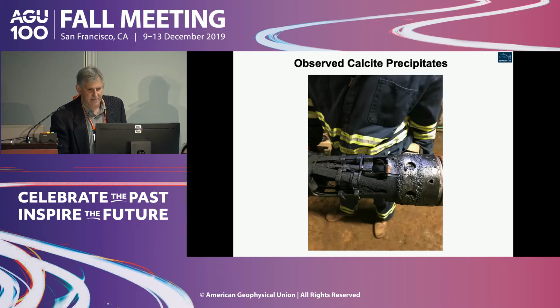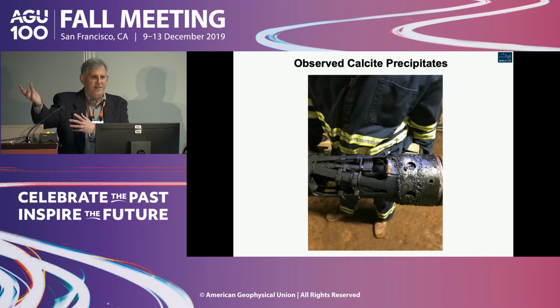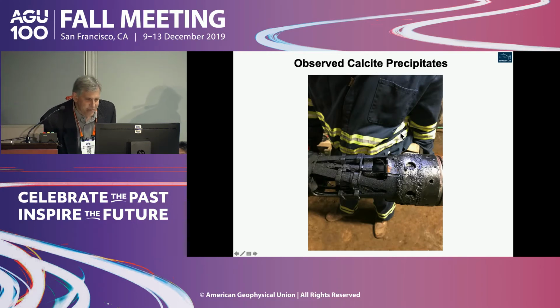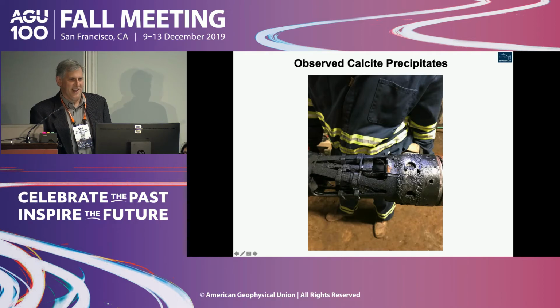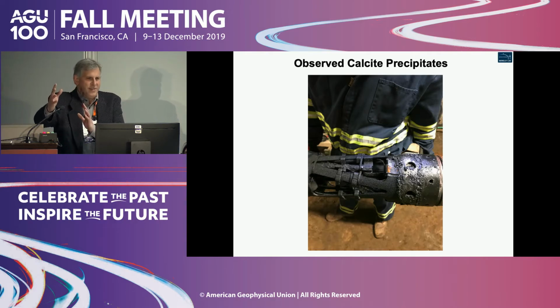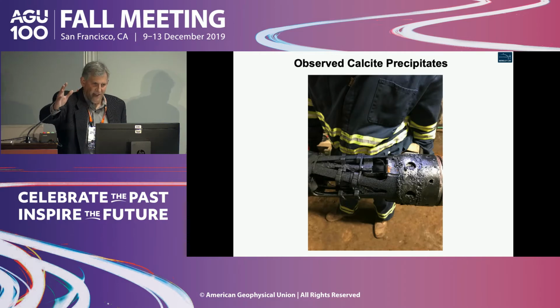So actually, when they pulled out some of the packers several meters away, they pulled out these grungy packers, and you'd think there'd be other minerals here, but mostly what they were able to find by XRD is just calcite. It doesn't look like calcite, but it's mostly calcite. But this is further away, so we really don't know what minerals are forming right near the inlet until they pull out some of those fractures. But certainly there has to be some of these iron hydroxides. We don't know if there's really schwertmanite at all, but this is consistent with dissolving calcite through acidity and then precipitating it out further.